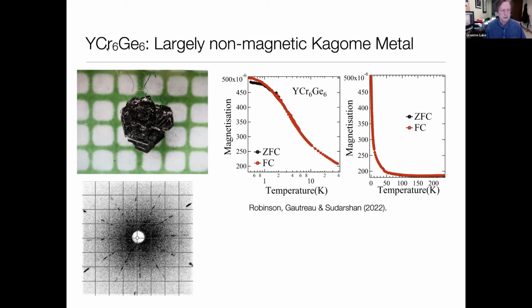In this material, the chromium is lying on the Kagome lattice. The yttrium and the rare earths are on a triangular lattice. So to look at the real Kagome properties, you certainly want to have a non-magnetic ion there, we think. Here you can see the 12-fold symmetry in the Laue pattern. We've just started managing to grow these materials in single crystal form. They are metals. If you put a voltmeter on them, you just get a resistance. And the magnetic susceptibility, although it looks big on the scale, is because we're very sensitive.